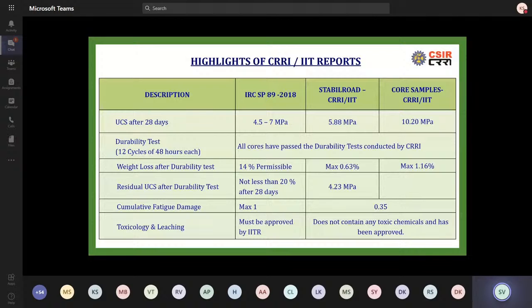So this has to be done 12 times. And after you finish it, they check for the weight loss. If you see the next one, the permissible weight loss is 14%. In our case, from CRRI, it's less than 1%, and on site it is around 1%, 1.1%. And this has been the case for all our cores so far.